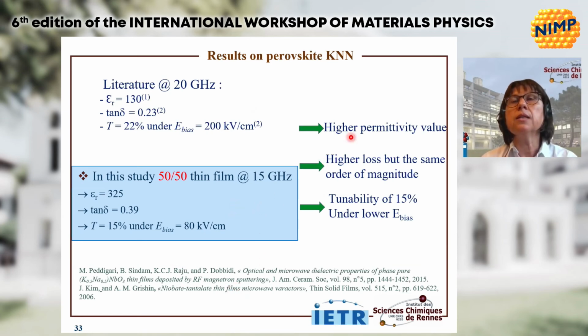We obtained, in comparison with a few data from the literature, a slightly higher permittivity value, higher loss but of the same order of magnitude, and a tunability of 15% to be compared to 22%, but with a lower E-bias, because we are working with only 80 kilovolts per centimeter with our devices, which are in coplanar geometry.